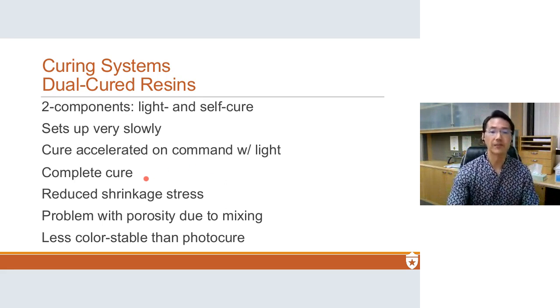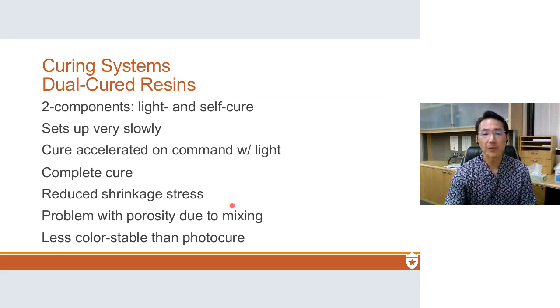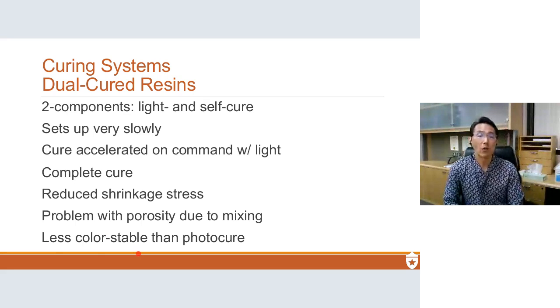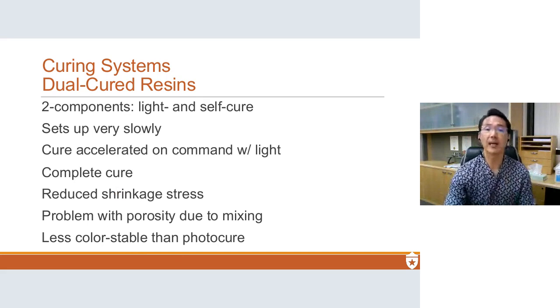immediately. Okay? The advantage of that is that you can have more complete cure if it's mixed well. Reduced shrinkage stress because part of it is curing more slowly and allowed to relieve the stress. However, there is a problem with porosity because you're mixing, and because you have the aromatic amine in there, it's less color stable than photocure. Now, we've developed actually a very low color, very color stable dual cure system in our lab. And similar systems are currently being used for something called bulk cure composites that we will talk more about later. So advances have been made in that area.